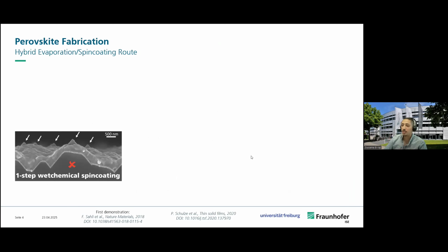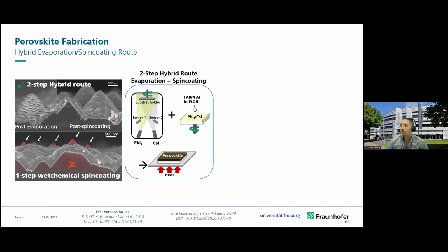Now, how do we make the perovskite absorber in a way that it conformally coats textured silicon? Well, researchers have found that using the standard one-step solution spin coating does not really yield a conformal film coating. As you can see here, we have the pyramid tips which are uncovered. Instead, in 2018, a collaborative effort between EPFL and CSEM laid the foundation for the hybrid method.